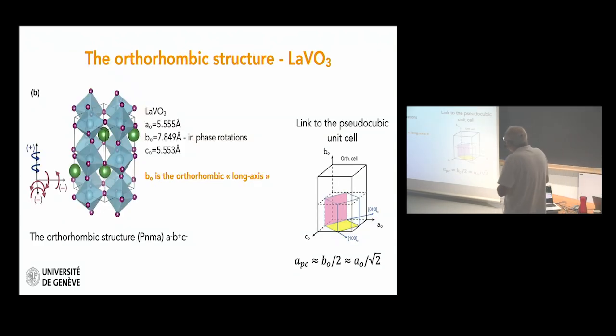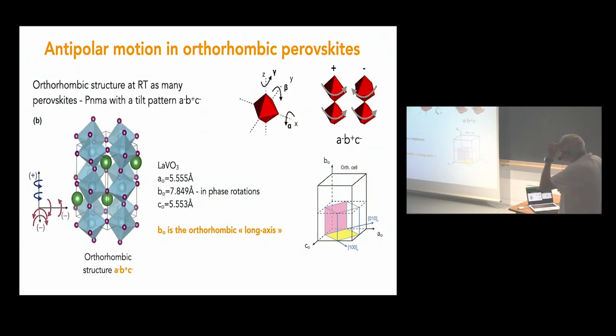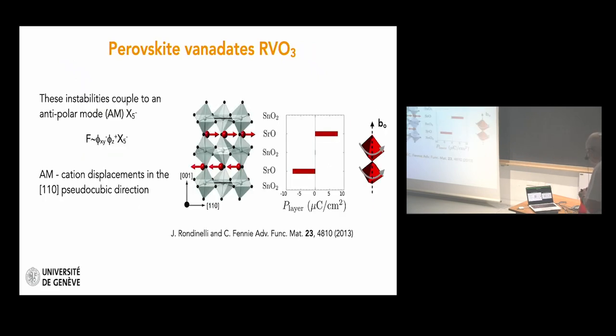This is one example of an orthorhombic structure, lanthanum vanadate. So you see here the orthorhombic structure. If you look at the orthorhombic lattice parameters, you see that the b-axis, the axis which has the in-phase rotations, is longer. It's called the orthorhombic long axis. What one should simply remember is that along this axis, you have in-phase rotations. And you have a relation here between the orthorhombic and the pseudocubic lattice parameters. Important is that coupled to these rotations, we have an antipolar instability, an antipolar motion, and this is what I would like to discuss with you.